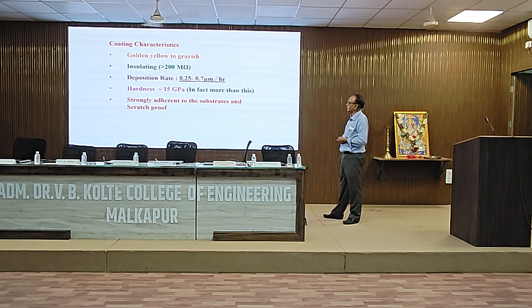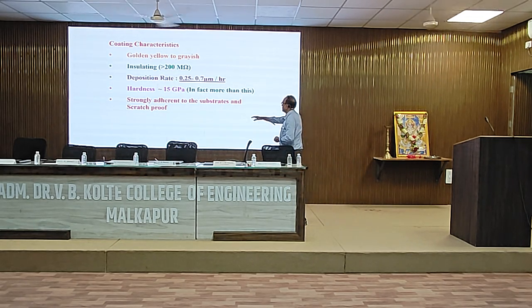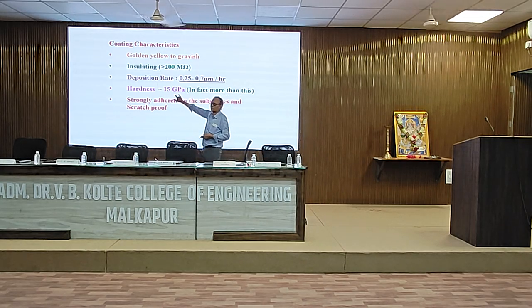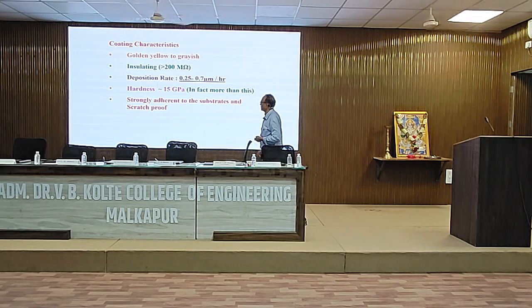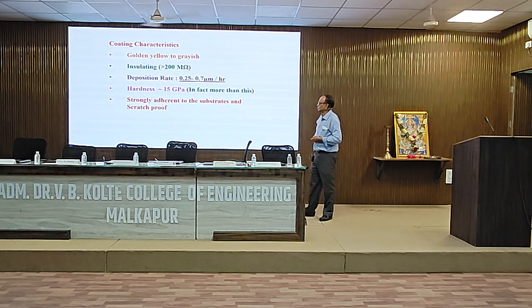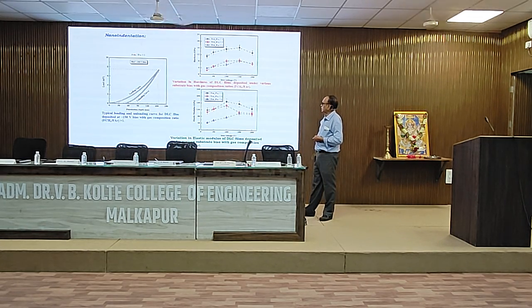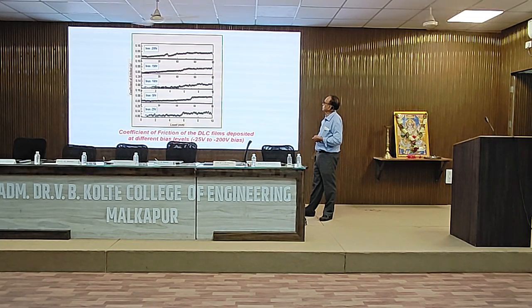Coatings were golden yellow to black, grayish, insulating. Deposition rate was 0.2 to 0.7 micron depending on the process parameters. Hardness was 15 GPa, which is almost 7 times harder than steel. Steel is 2 GPa. And the coatings are strongly adherent to the substrate and scratch proof. I will not go through this one.